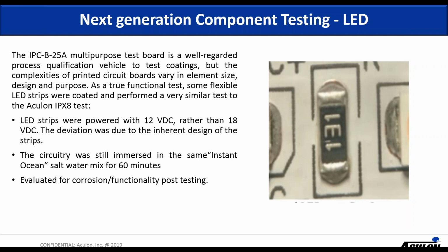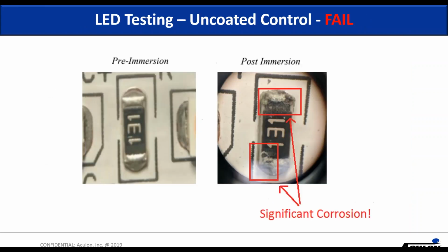So we coated the LEDs, and these were immersed in the same saltwater mix for 60 minutes, powered at 12 volts, just because that's the inherent design of the strips. And afterwards, they were evaluated for corrosion and functionality. You can see here an uncoated part. Looks great before, afterwards it's failed. The lights aren't working, and there's just massive corrosion on every single resistor. Just across the board failures on these LED test strips.